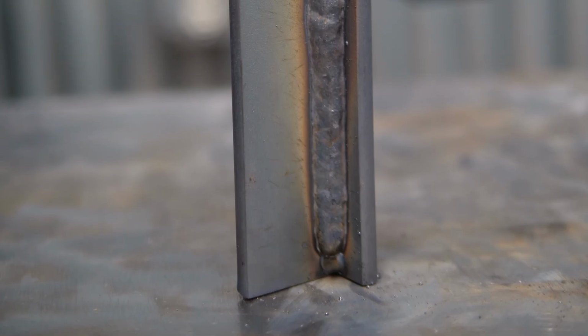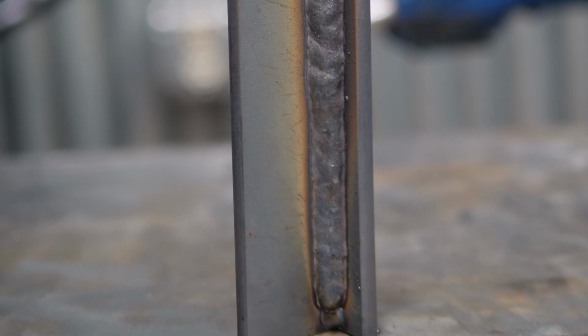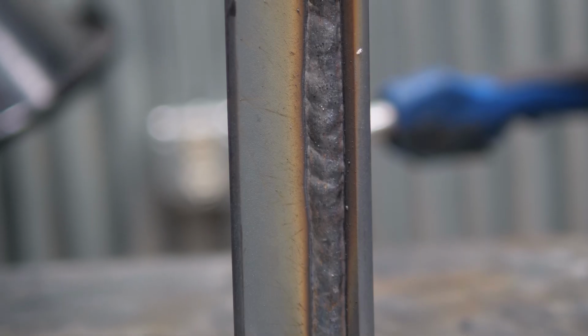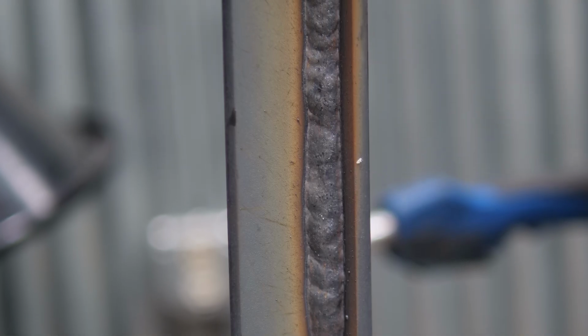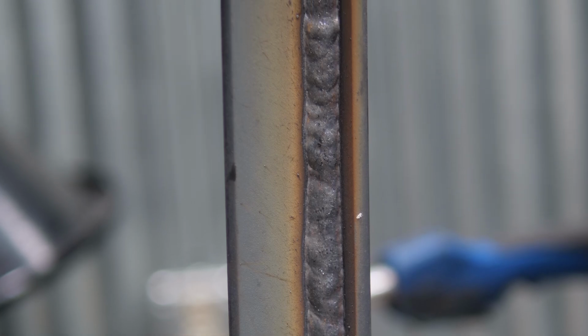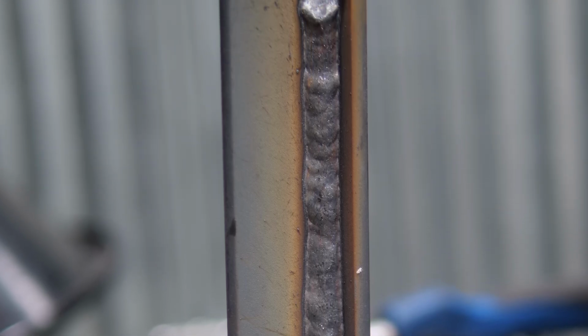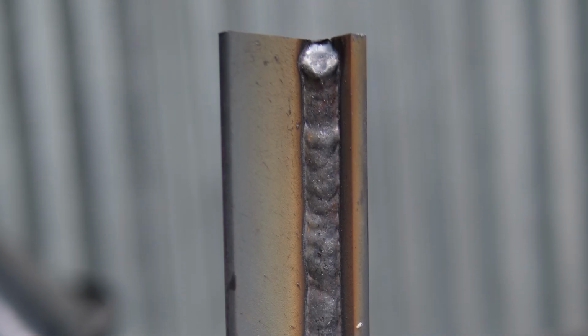It is really nice and buttery smooth. I can see a little bit within the arc that the stream of metal is not quite axial. It does drift off in one direction. See if that changes at all when we go to the MEGAFIL 713R. Super easy slag removal. Like any dual shield wire, you just touch the slag and it falls right off. Very minimal spatter. There are a few BBs, as to be expected on some mill scaled plate. Now my average amperage was 234 amps, and I really only lost a tenth of a volt, so 25.9, which is completely acceptable. Let's switch over to the MEGAFIL 713R and take a look.